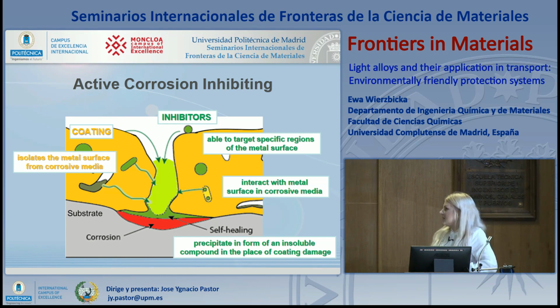Now, the big target in the development of coatings is the introduction of active corrosion inhibitor species into the coating. In contrast to the base composition of the coating, we can introduce the inhibitors. The base coating is responsible for forming the protective layer from the environment, while the inhibitors are able to target specific regions on the metal surface, interact with the metal surface in corrosive media, and precipitate in the form of some insoluble compound in the place of coating damage.